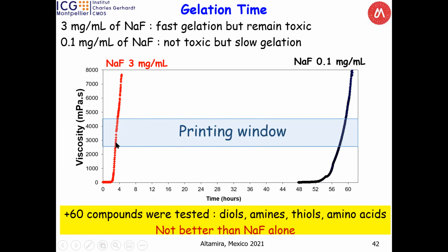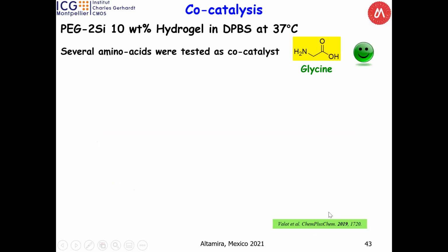It's okay for us. It's very, very fast, but it's not possible by adding only glycine. You have to increase the amount of sodium fluoride. So we have to stay here. So we selected several types of compound: diol, amine, thiol, amino acid, and we didn't find any better than sodium fluoride alone. However, if we add both F- and glycine, it's possible to obtain a co-catalysis system at 37 degrees with 10% of silylated PEG.